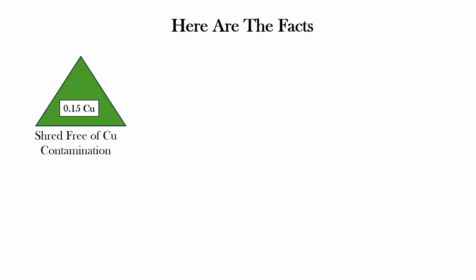Let's talk about what's happened to shredded over the course of time. If you took every ounce of free copper contamination in the form of wire, motors, etc. from a typical commercial grade of shredded, and you looked at what was just left as a part of the alloyed steel content, that copper level would be about 0.15. This has raised since the 1980s when I was looking at this when I worked at the David Joseph Company, when that free copper level was about 0.11. The change from 0.11 to today's world of 0.15 is just the influence of a higher percentage of steel from electric arc furnaces coming into that scrap stream and being shredded.